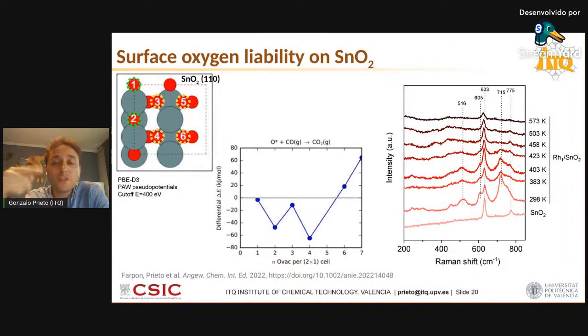But then losing further oxygen, trying to lose the first in-plane oxygen, becomes uphill energetically, as I'm showing here on the plot for oxygen vacancy number 3. It goes uphill, and it is also subjected to energy barriers, which would make it less feasible, if at all feasible, under the hydroformylation conditions we operate this catalyst at. This is something that we could actually confirm experimentally using in situ Raman spectroscopy.